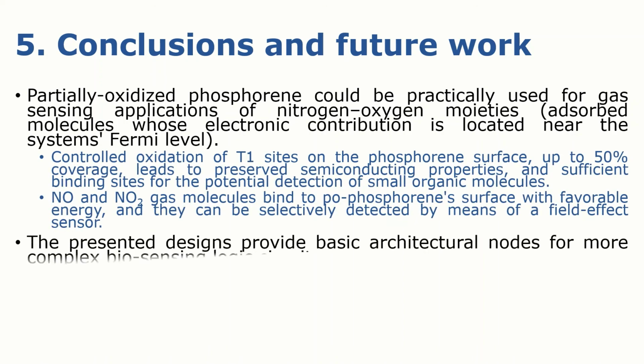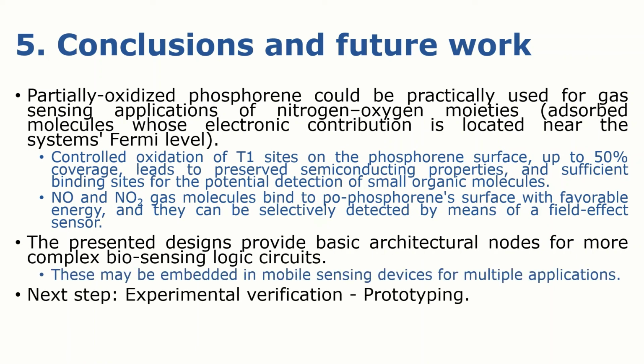We have seen that partially oxidized phosphorene could be used for sensing applications of nitrogen-oxygen species, and also other absorbed molecules with electronic contributions near the Fermi level. Also, surface oxidation in the dangling position, or T1, is energetically favored, and concentrations up to 50% show conservation of semiconducting properties, while still having sufficient available sites for binding other small organic molecules. However, we will still require a very high control of surface oxidation for their practical use.